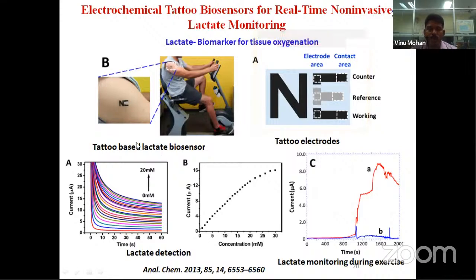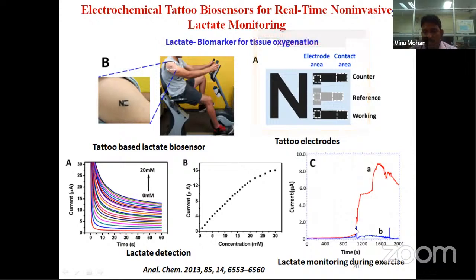So lactate is a biomarker for tissue oxygenation. Insufficient tissue oxygenation can be detected by monitoring lactate from our sweat samples. So we developed another tattoo sensor, and when the person is doing stationary biking, we can collect the sweat samples and directly do the lactate analysis. You can see in this figure, initially for some 10 minutes there was not much perspiration, and when the perspiration starts, we can see the current signals proportional to the lactate concentration. When we increase the exercise intensity further, we get more and more lactate.